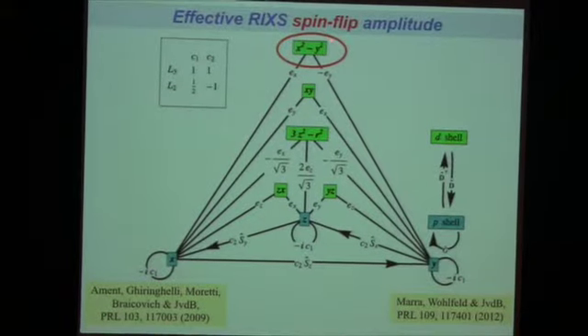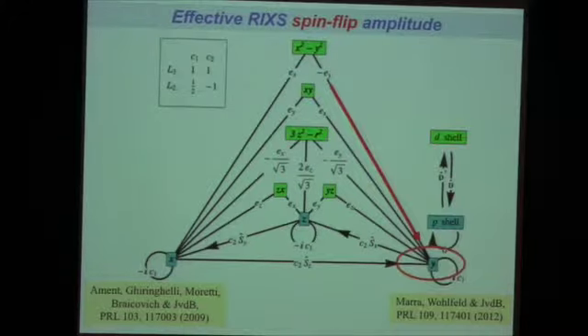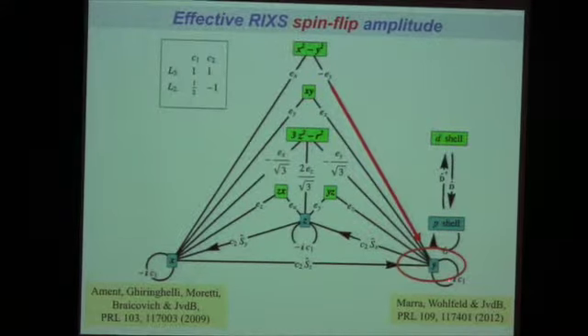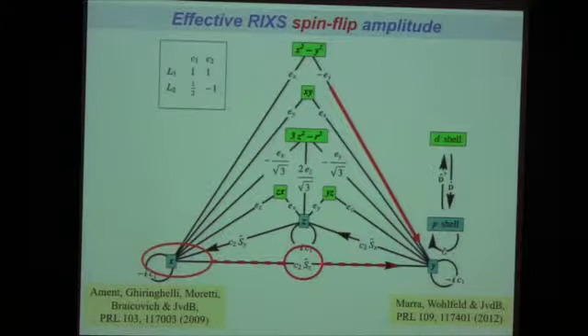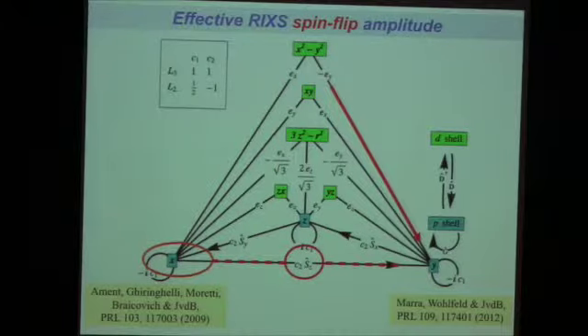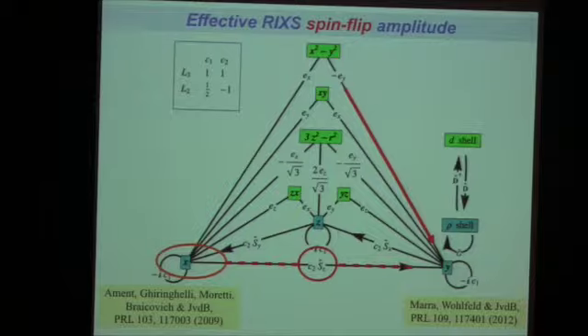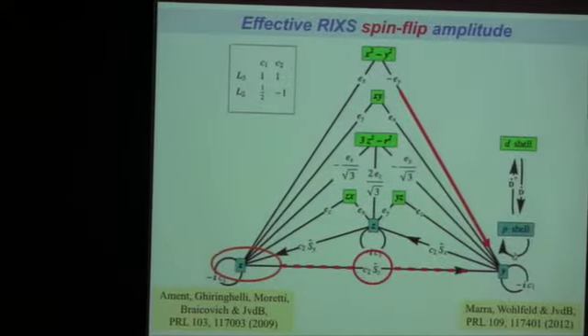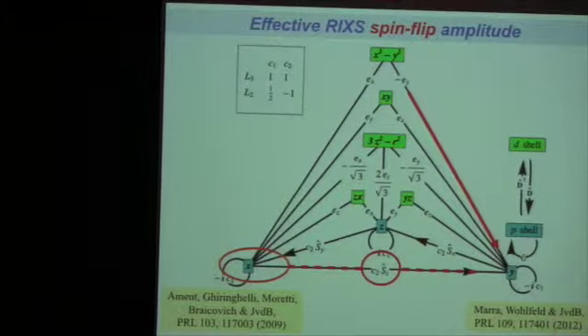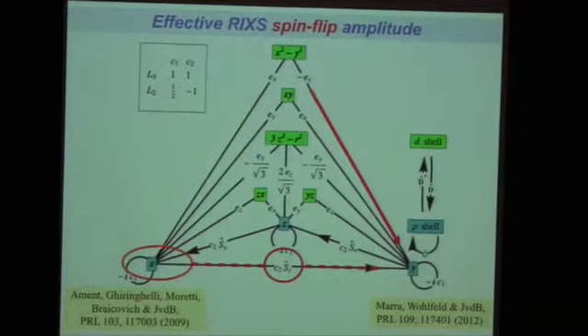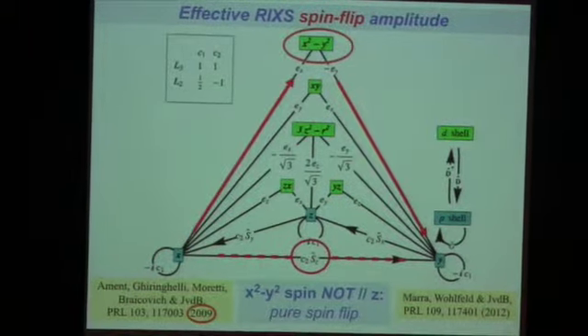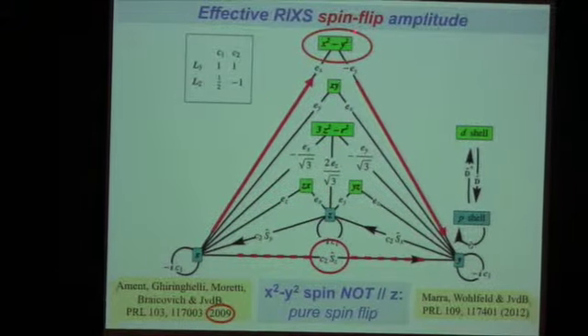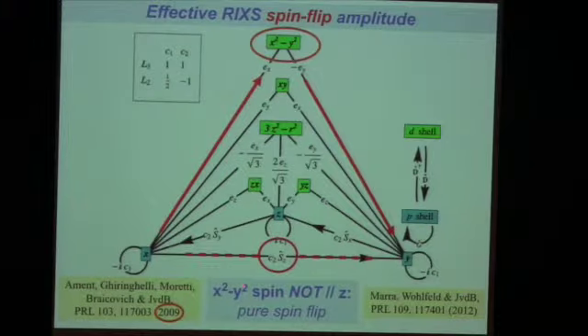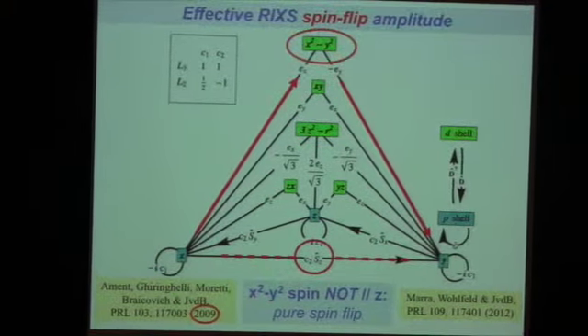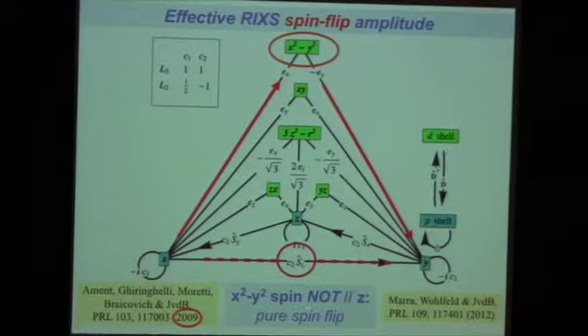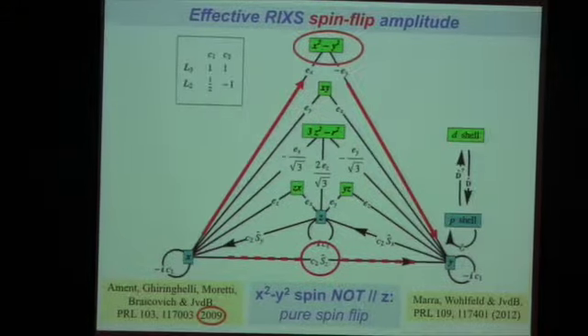In this diagram, I start now with an x squared minus y squared orbital, where the hole sits, and do an absorption into the p_y. But now, instead of making a small circle here, I go along this line, and I pick up an operator. This operator is S_z. It's a spin operator acting on the electron in the x squared minus y squared orbital. So the z-axis is a real axis in my system. It's the axis perpendicular to the xy plane. This operator acts on my spin. I end up in this orbital, and now in the decay, again, I go to x squared minus y squared. So I go from x squared minus y squared to x squared minus y squared, but pick up the spin operator, and if the spin in this orbital is not parallel to z, I can make a spin flip. If the spin is parallel to z, then of course I do nothing to the spin.